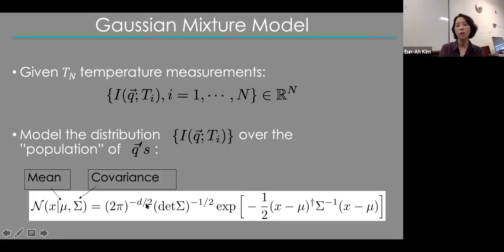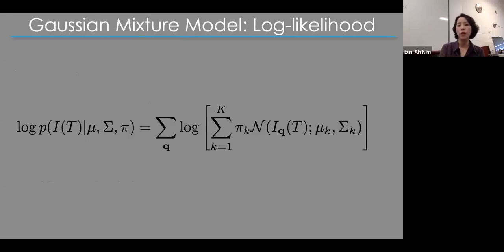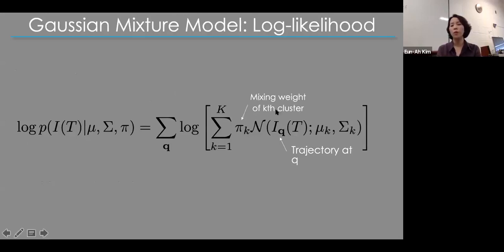Now we want to think about clusters. So now there won't be only one multivariate Gaussian. We would have multiple multivariate Gaussians. And then we look at the log likelihood, defined as the normal distribution function evaluated for a given trajectory at Q with assumed values of the mean of a given cluster and the variance, and the mixing weight of a given cluster, and summing all of those logs over the different Qs gives us the log likelihood.